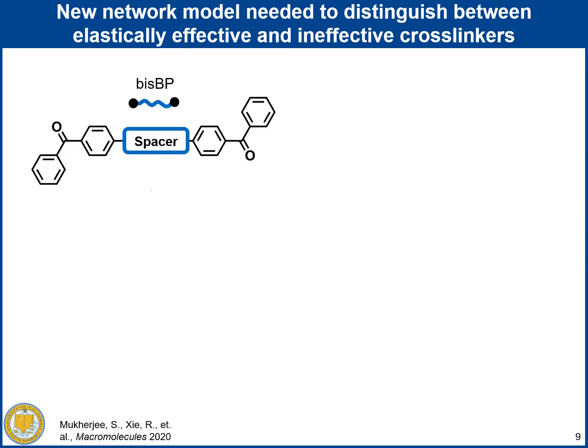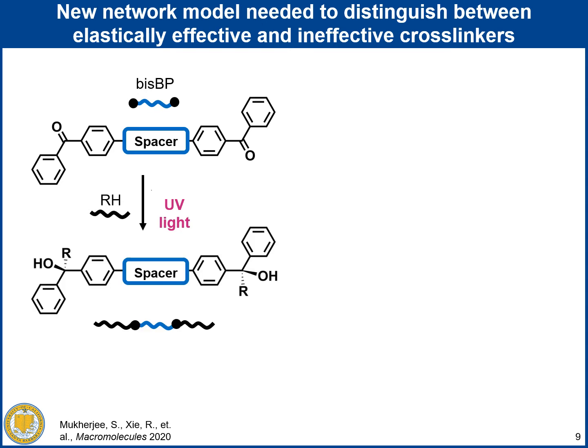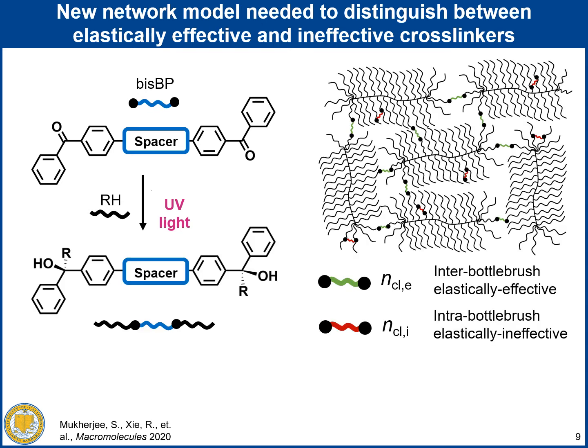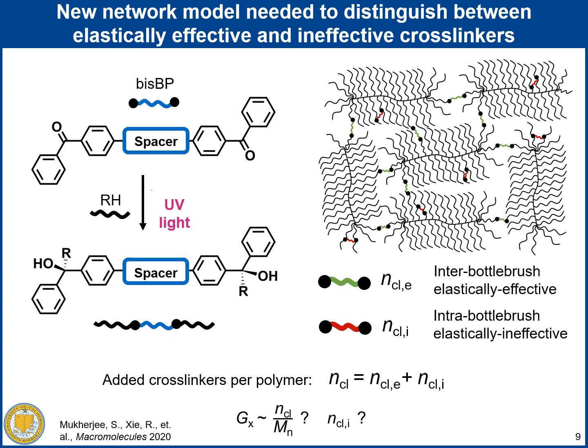But the main concern of applying the previous approaches in our system is the indiscriminate nature of the benzophenone-mediated crosslinking, meaning that the benzophenone unit can link with any nearby hydrocarbon unit upon UV irradiation. So there will be a number of crosslinkers that we added that are not elastically effective and are actually embedded inside the brush region. So the total crosslinkers that we added are therefore a sum of elastically effective and ineffective crosslinkers. So how do we relate G_x, which is an equilibrium network modulus, to the crosslink loading and the total number of elastically ineffective crosslinks?